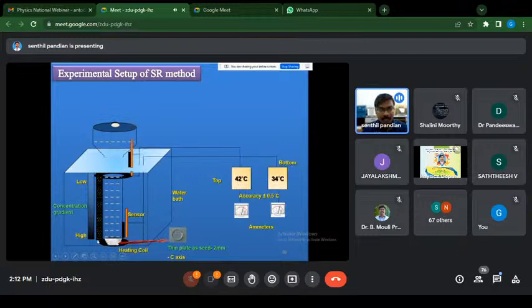And then we have to apply the temperature at the bottom and top portion. The top temperature is only for solvent evaporation, and the bottom temperature is for growing the crystals. So the only thing is we have to maintain a uniform temperature between the seed crystal and the solution interface. If we cannot maintain the uniform temperature, then multinucleation will easily be formed because of the temperature fluctuation. Solvent inclusions will be formed in the grown crystal, milky opacity, microcracks, and all kinds of dislocation issues will happen in these SR method grown crystals.